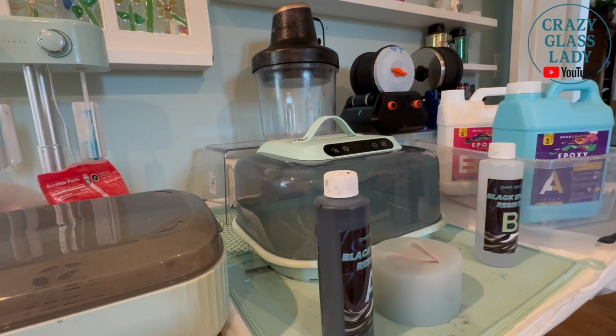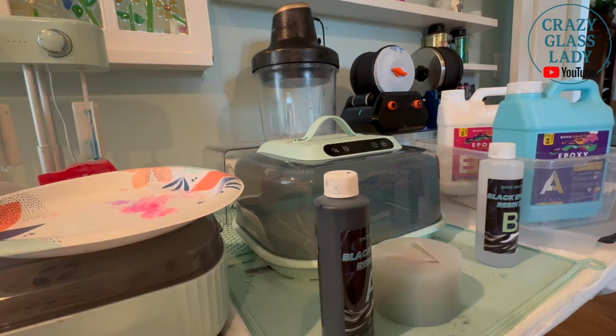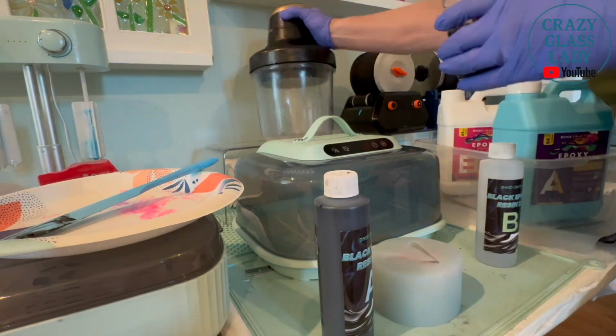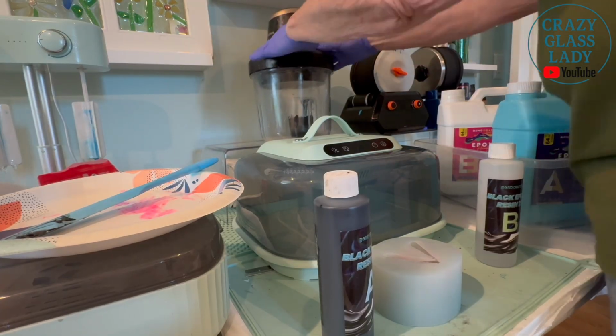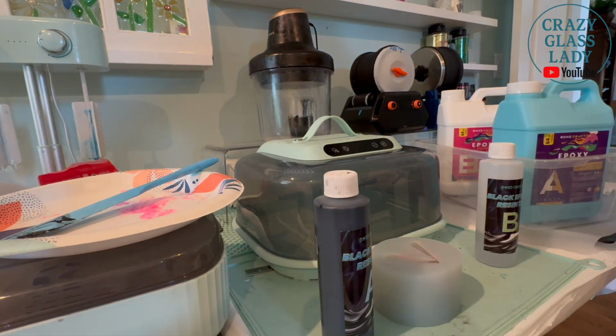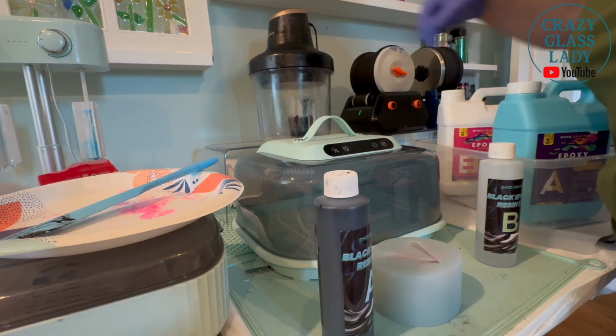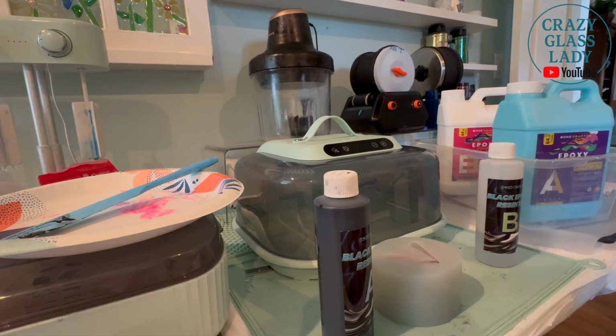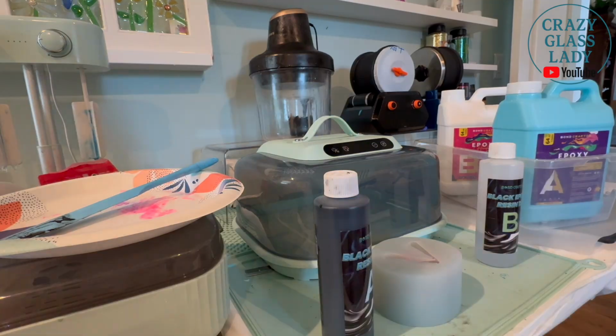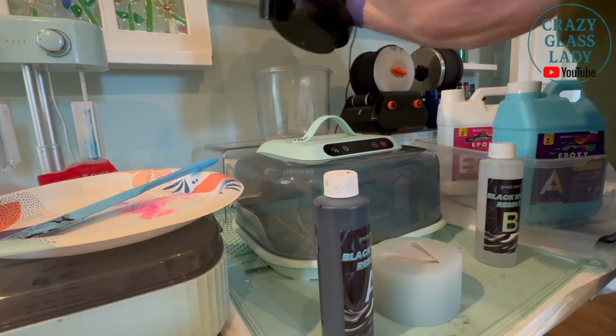It's a two-part resin. You just mix it together like any other resin for 3 minutes. It's difficult to tell whether it's mixed or not because you can't see any lines in it, so you need to do it for 3 minutes, and then I put it in the bubble removal machine. Although each time I've ever mixed this, it doesn't have any bubbles. I'm not sure why, if the pigment prevents it or what, but anyway, I did put it through the bubble removal machine for 5 minutes and then poured it into the resin mold.